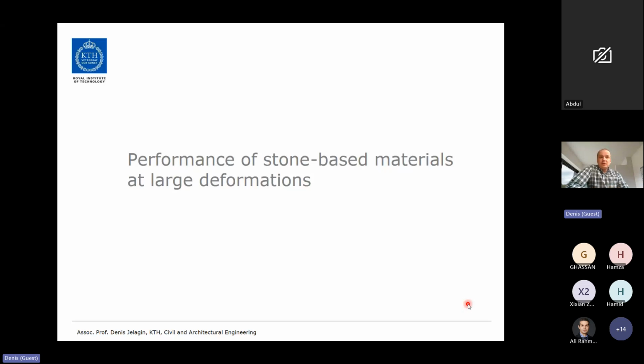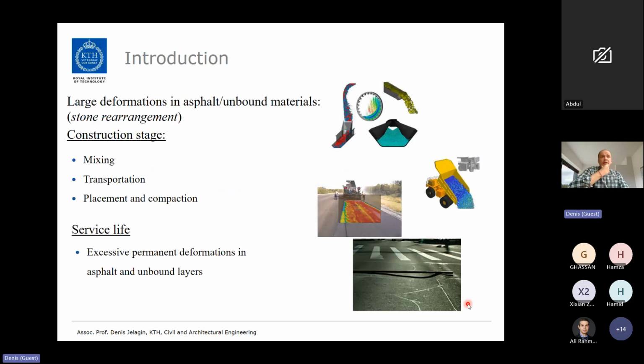Now we go into a little bit more technical part of the presentation and start to speak about tools we develop for analysis of stone-based materials at large deformations. So first of all, when we say large deformations, we have our own definition of what large deformation is. It's not the classical solid mechanics definition where angles become non-negligible. We rather look at material where we had two neighboring aggregates in contact with each other at the initial configuration, and then after the deformation process, the aggregates rearranged so much that they lost their contact, so they changed their neighbors completely. And those types of deformations happen quite a bit with our material.